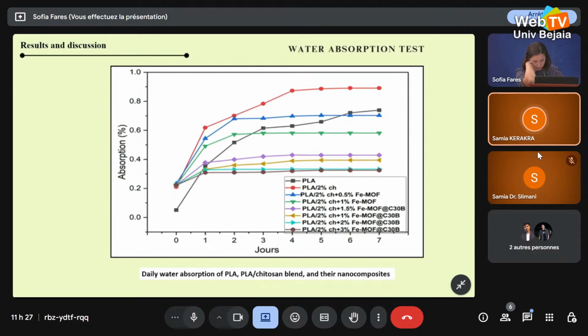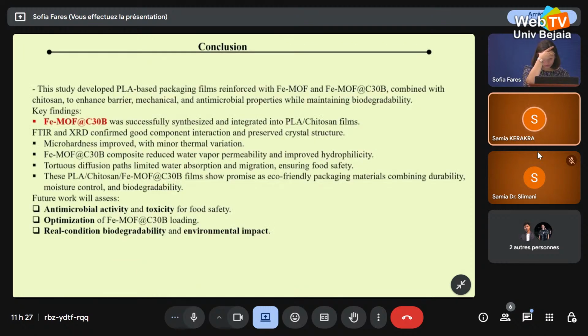Overall, the results indicate enhanced barrier effects and stable structure over time, confirming the good compatibility and interaction between the polymer and fillers. As a conclusion, this study developed PLA-based packaging films reinforced with both MOF and MOF clay composites combined with chitosan that can enhance barrier, mechanical and antimicrobial properties. We didn't put results here, but it really enhances even antimicrobial properties while maintaining biodegradability. We are right now carrying out some biodegradability testing.